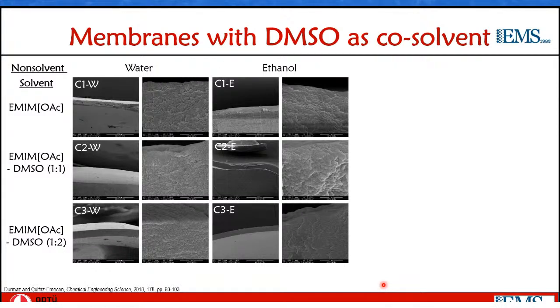So as I mentioned, the ratio of the solvent's out-diffusion from the polymer solution and the non-solvent's in-diffusion into the polymer solution is quite effective in determining the membrane morphology. And when you have a very viscous solvent in the polymer solution, this slows down the non-solvent in-diffusion and then changes the membrane morphology.